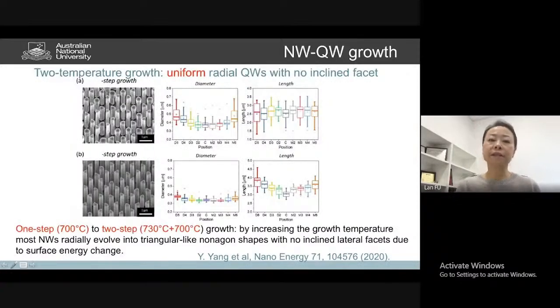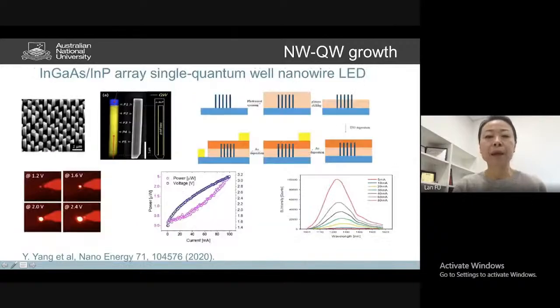So my student, thinking about understanding the growth, introduced an extra step during his nanowire growth, basically changing the surface energy of the nanowire. And thereby he's able to grow much more uniform nanowires, from this quite non-uniform morphology into this predominantly triangular top and uniform nanowire array. You can see the enhanced diameter as well as length uniformity. So after that, he said, okay, I'm pretty ready for making them into an array device.